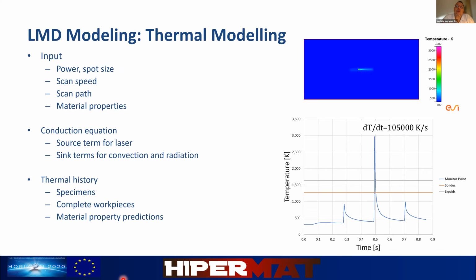With this cooling rate, we can then run thermodynamic calculations, as David showed in this presentation, to verify the properties locally and globally in the model. So the material property predictions for as-built material can be corrected if needed, if these cooling rates are significantly different. The next slide, please.